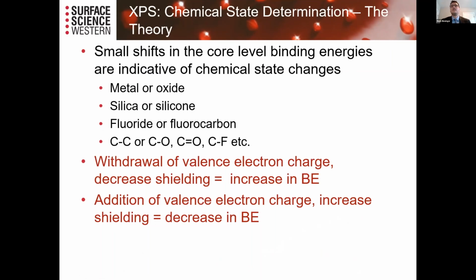XPS chemical state determination theory. So small shifts in the core level binding energies are indicative of chemical state changes. So you can tell whether you have metal versus oxide, silica versus silicone, etc. As you withdraw valence electron charge, you decrease shielding, increase the binding energy. As you add valence electron charge, you increase the shielding, decrease the binding energy.